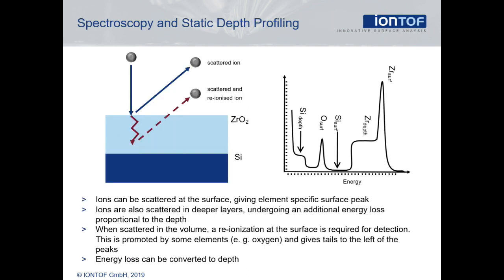In addition to the process of scattering at the outer surface, which was responsible for the peaks in the spectrum, another process takes place: scattering at an atom in deeper layers. For this to happen, the ion has to penetrate the surface, travel to the atom, scatter — again with an energy loss given by the scattering formula — then travel back to the surface and leave the solid.